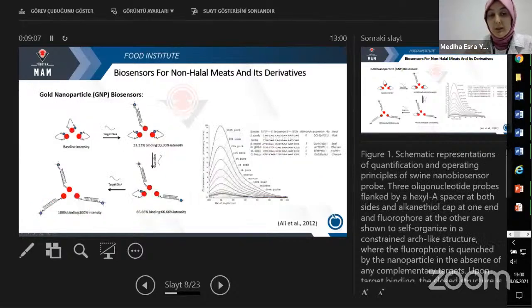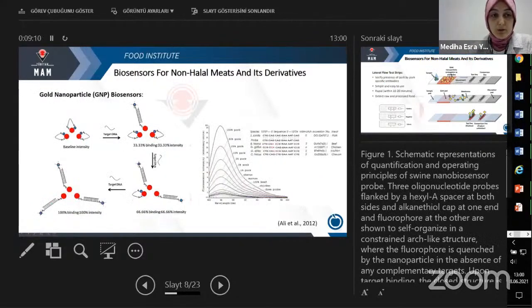So let's see another example of gold nanoparticle biosensors. In this study, they used a porcine marker with a fluorescent dye tagged on it. And when it is bound around the gold nanoparticle, the gold nanoparticle quenches the fluorescent dye. When the target DNA, the porcine DNA, is added, it binds to the marker DNA, taking the fluorescent dye away from the gold nanoparticle, and then the fluorescent dye starts to give the fluorescent signal. And when there is an increase in the sample, the signal increases.